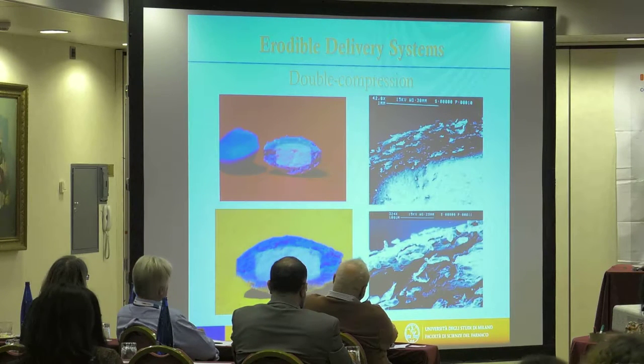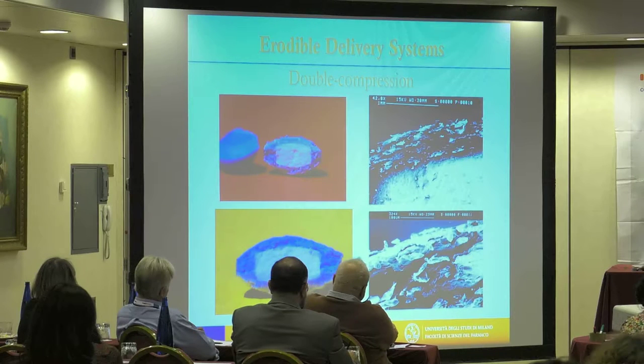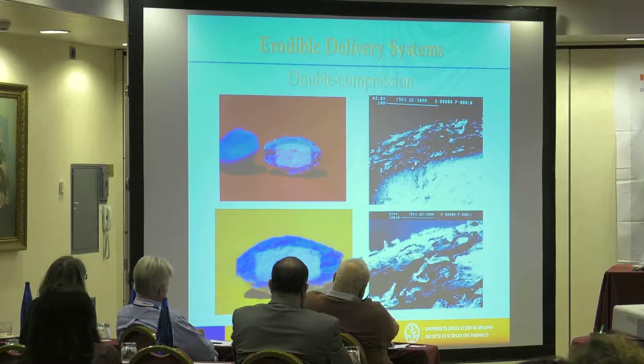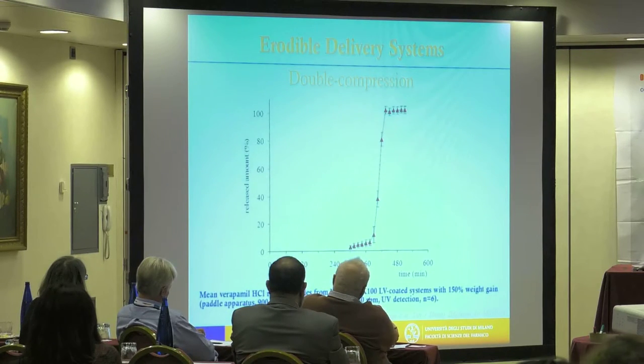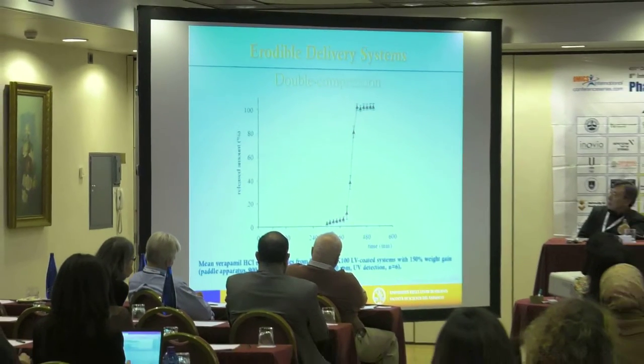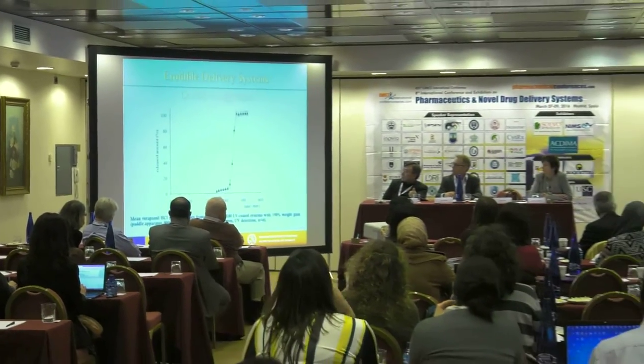The double compression technique was employed in the earlier attempts to produce erodible delivery systems for time-controlled release. In this case, positioning of the core in the die of the tableting machine was a critical step. Anyway, by correctly centering it within the polymer powder bed, biconvex tablets provided with coatings of homogeneous thickness could be obtained. And in vitro, the onset of drug release was delayed for a reproducible period of time.